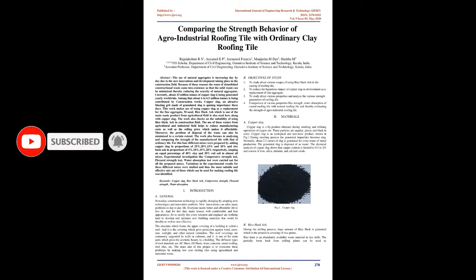Experimental investigations like compressive strength test, flexural strength test, and water absorption test were carried out for all the prepared mixes. Variations in the experimental results for these different mixes were studied, and thus the most suitable and effective mix out of these, which can be used for making roofing tile, was identified. Keywords: copper slag, rice husk ash, compressive strength, flexural strength, water absorption.